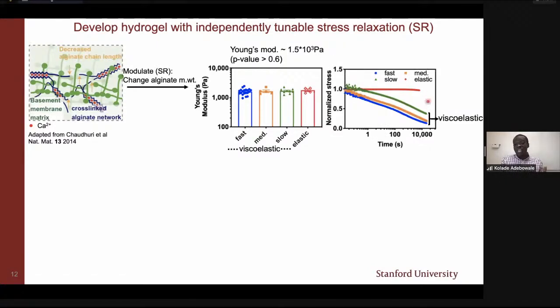Importantly, however, the viscoelastic materials have different stress relaxation properties. And we can quantify these differences, for example, by looking at the time that it takes for the peak stress in the material to reduce to 1/2 its initial value. We call this number T1/2. And this T1/2 is about 2,000 seconds for what we call a slow stress relaxant hydrogel. That's the data in green. And about 100 seconds for what we call a fast stress relaxant hydrogel. That's the data in blue.